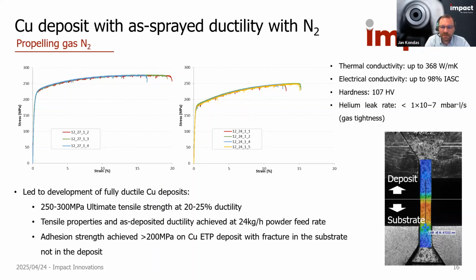Except that the adhesion of this material to the substrate, in case we are using pure copper, so soft ETP copper, is higher than the cohesive properties of this ETP copper. So basically, as you can see on the bottom image, during the tensile testing, the fracture occurs not in the interface, but in the substrate material, which is softer. This type of copper deposit has also excellent electrical and heat conductivity, opening many possibilities in heat exchangers and coolers. You can see we can reach 98% of the international annealed copper standard and 368 watt per meter Kelvin thermal conductivity.